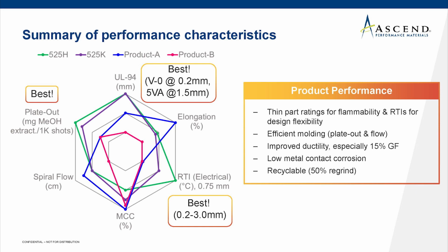We also show efficient molding as reflected in the plate out behavior and the flow. And then also improved ductility reflected in the elongation, especially for the 15% glass fiber. And also we exhibit low metal contact corrosion, and these materials are recyclable with a 50% regrind rating. And they are European REACH and RoHS compliant. So this concludes our first half describing our 500 series product family for a variety of high voltage electrical connectors.